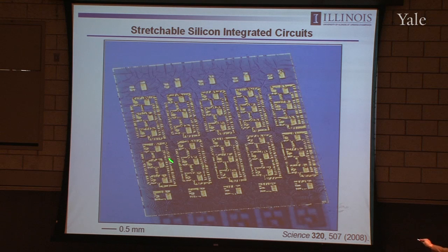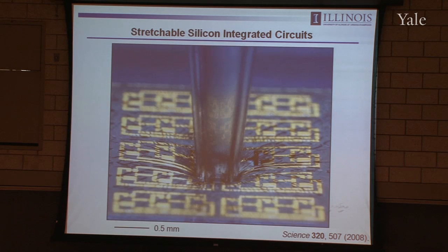So in this case, it's an array of 10 CMOS ring oscillators, 3-stage. There's some inverters down here and isolated N and P channel transistors up here. It's illuminated in a way that sort of highlights the wavy structure that forms as a result of that process. So you can imagine if you stretch this thing in any direction like that, those wave structures can change their geometries to accommodate that overall deformation without fracturing the silicon or the other components of the circuit. And so you have an overall integrated system that is dominated by the mechanics of the underlying rubber.